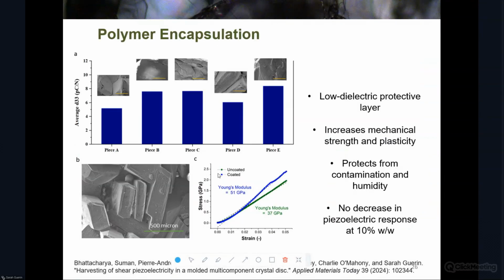And then finally, this is where I'm going to finish, is the final challenge with these is, of course, if you've grown a molecular crystal, I would say 6, 7, 8 times out of 10, you're going to be growing it in water. That means that your crystals, when you grow them, are water soluble. And for any application, but particularly some of the stuff we do around structural health monitoring, leak detection in pipes, medical devices and urology, there's a lot of water around. So we also needed to develop a standardized methodology for coating these discs and plates in order to make them, again, viable for technology.